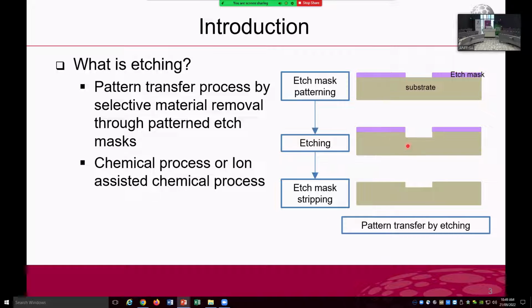And then in the last step, we just do not need this etch mask pattern anymore. And then finally this etch mask is stripped off and removed, and then recover the original surface of the substrate for subsequent fabrication steps. And this material removal in etching can be a chemical process or sometimes ion-assisted chemical process. Let's not worry about this ion-assisted chemical process at this stage. We're going to talk more later about this.